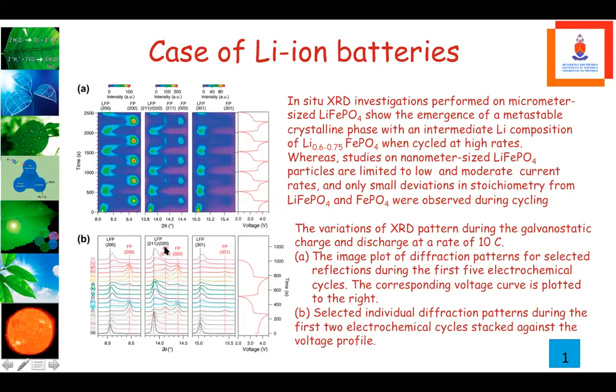The picture that you see here shows the XRD patterns of the galvanostatic charge and discharge at 10 C. So this here shows your intensities, and here are the maps of the up and down of charge and discharge.